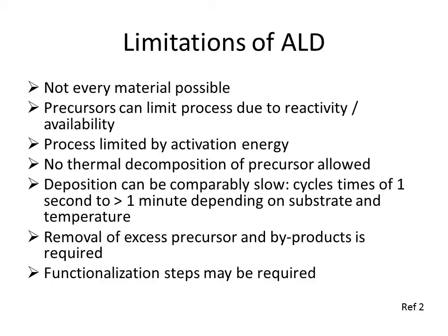However, this method has some limitations. Some materials take significantly longer to deposit. Chambers must be vented effectively in this process lest precursors mix and create deposits. Not every material is physically possible to deposit in this manner. Some substrates may require to be functionalized for reactivity with the precursor. Also, some precursors require a higher temperature to be reactive with the substrate. This leads to variations in ALD, one of which is PEALD.